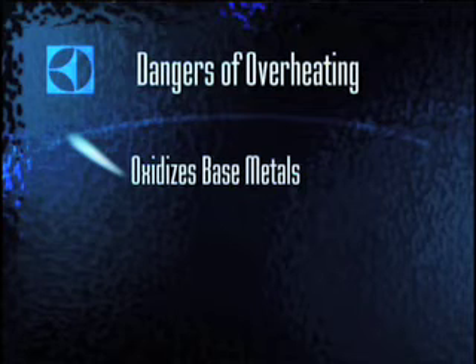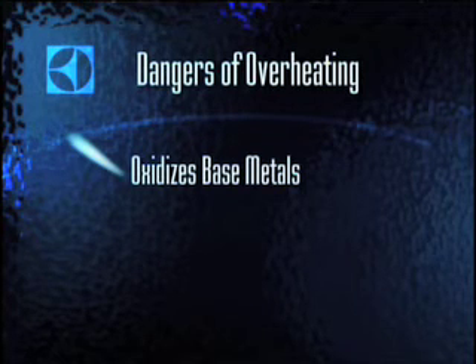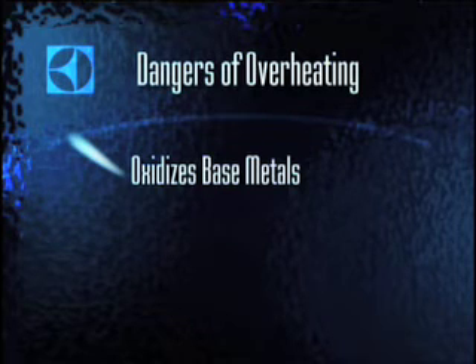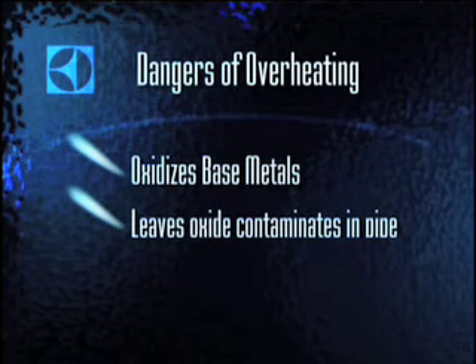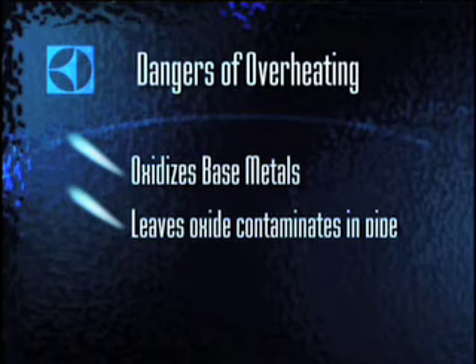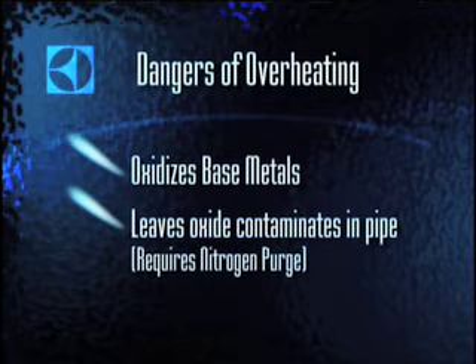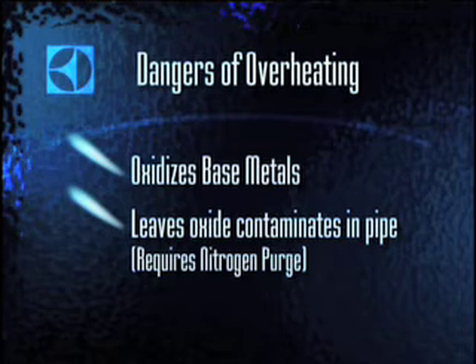First, it oxidizes the base metals, and the oxidation interferes with the flow of filler metal into the joint. Second, oxides inside the joint will flake off and potentially block the cap tube. Only a nitrogen purge will have enough pressure to loosen and eliminate all of those oxides.